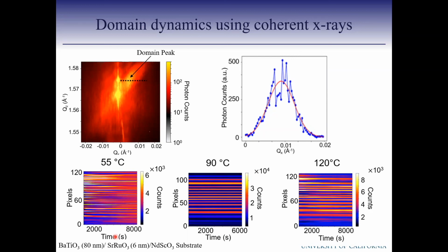But for some of our other samples, if you have some sort of Bragg peak domain, like an orbital ordering peak, then you have enough photons to do those kinds of measurements. But for glasses or amorphous systems, you really need to average to 1 or 2 seconds to even get enough photons to do any kind of analysis. So then it doesn't matter how fast your detector runs, you're limited by the scattering from the sample.